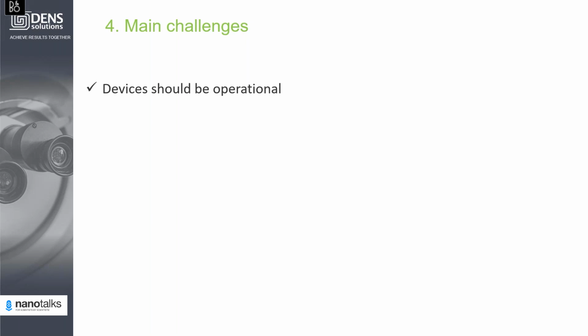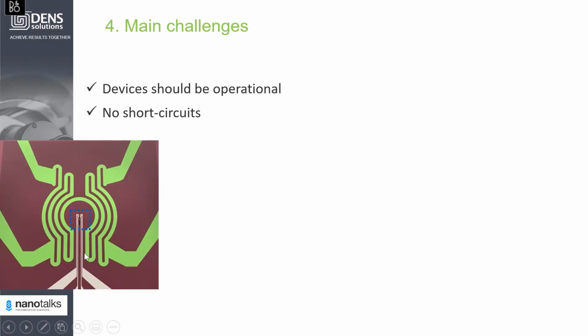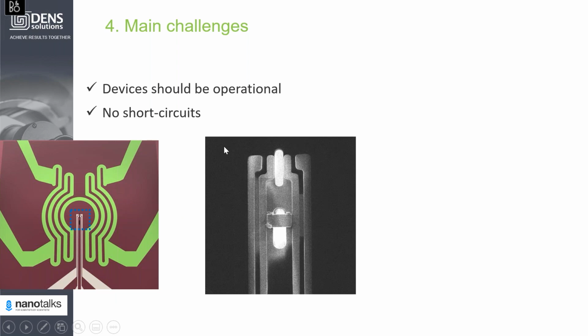One of the issues that can prevent the user from being able to measure the device is so-called short circuits. So in order to measure the property of your sample, there should be no short circuits on your chip. Here you see the schematics of the heating and biasing chip, and this is our sample area. Here you see an FIB image of the same sample area. We have 4 biasing electrodes. Around here we have a heater. This is a lamella welded with platinum to the nanochip. And as you can see, we have platinum contamination, a so-called platinum halo, around the lamella, and it extends from one electrode to the other.